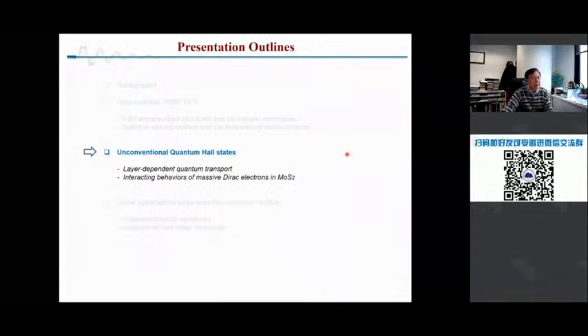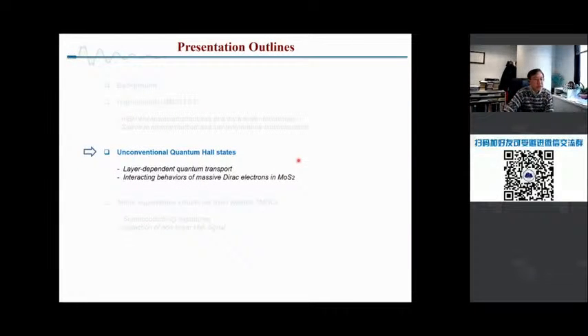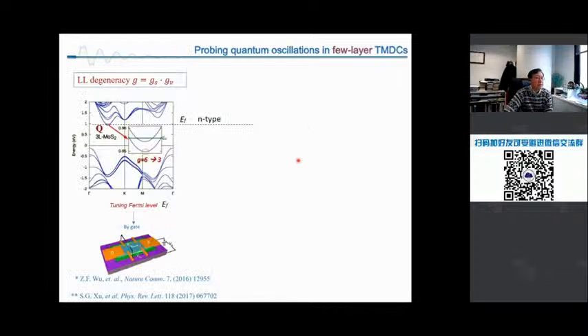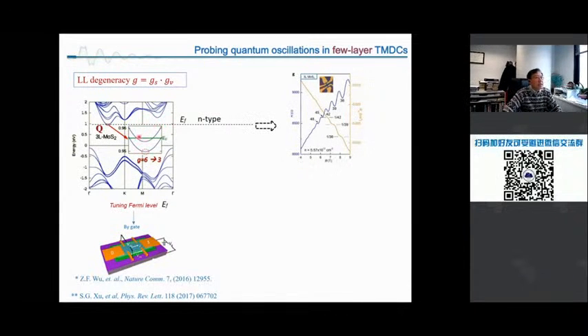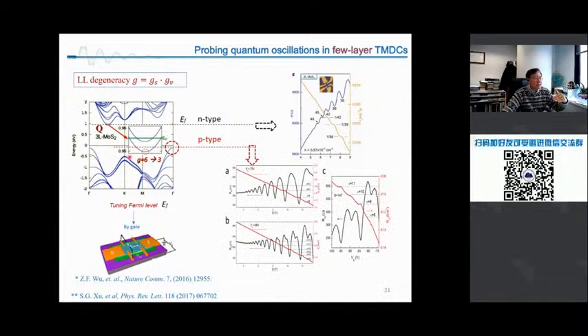So next, I show you two examples. The first one is pretty easy. If we make a nice device and tune the Fermi level, we can change the Fermi level to the conduction band, so we measure the electron behaviors, or we tune it to the valence band, here we can say gamma or K, and then we see nice oscillations. And this is the filling factor, and from this you can see the degeneracy and so on.